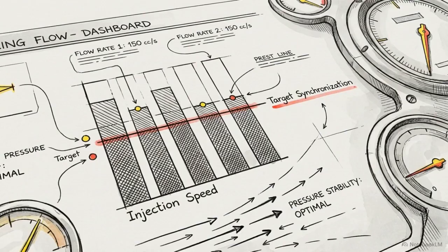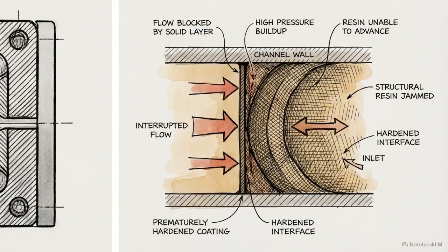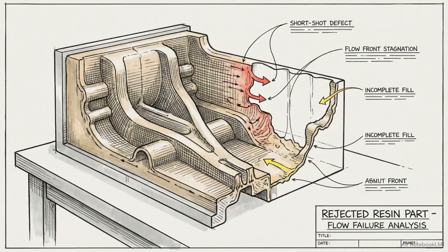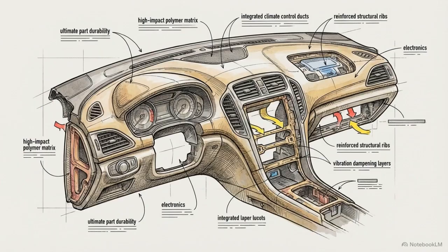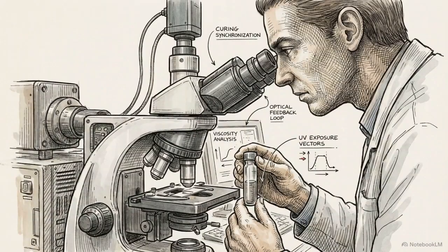Executing this requires exacting precision in fluid metering. The injected coating must spread uniformly without impeding the primary structural resin flowing right behind it. If the curing schedules of the two liquids fall out of sync, the coating will prematurely harden and interrupt the resin flow. This causes a short-shot defect, where the structural resin halts and the mold completely fails to fill. IMC pushes the boundary of part durability and functional utility, but it demands trading the mechanical hurdles of solid films for microscopic control over chemical metering and curing synchronization.